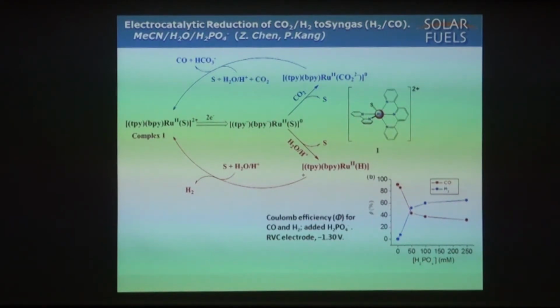We also showed with the same complex, if you had no CO2 but you had weak acids, and water would be a weak acid, that rather than do the CO2 reduction, there's no competition with no CO2. What happened was the complex that came out of that reaction was the hydride. So reaction with water produced the hydride, a different transition state, different pathway. That hydride then protonated to make hydrogen and recycled, and that was catalytic. And then we showed in acetonitrile, if you added a little bit of a weak acid, dihydrogen phosphate, under controlled conditions with some added water, you could in fact control the amount of carbon monoxide that appeared and the amount of hydrogen that appeared, because they went through a common intermediate and you could dictate what happened.